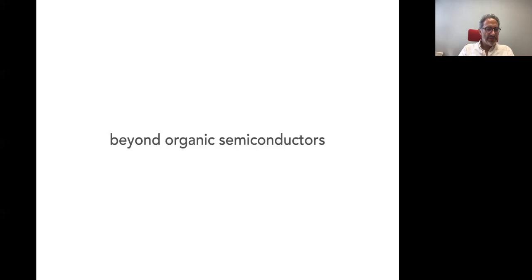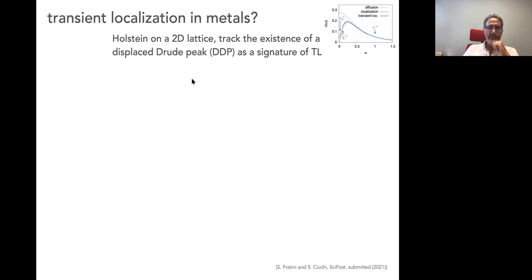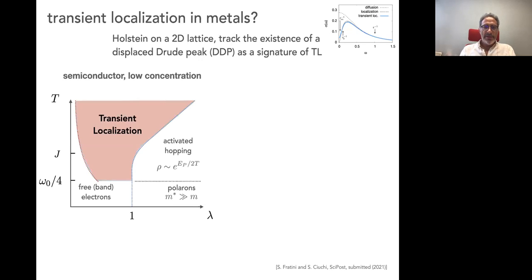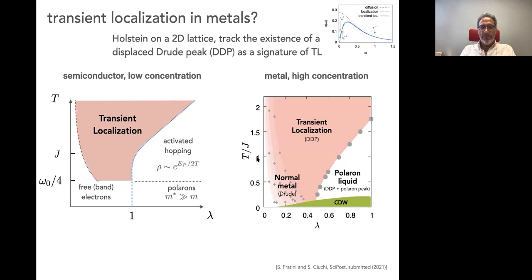So just in the minute or so that I have left, we have been working recently on going beyond organic semiconductors with the same ideas, and in particular in metals and doped polymers. So again, I'll use my favorite Holstein model, and I'll track just the transient localization by the existence of this displaced Drude peak that I was telling you about a few slides back. So this you have already seen. This is the sketch for semiconductors. This is where we started from. Now we did calculations for metals, and this is the phase diagram we find. These are real numbers. I mean, this is our real calculations, not a sketch. And you see that the phase diagram is essentially the same. So this transient localization is not limited to organic semiconductors. It should be seen in metals also.